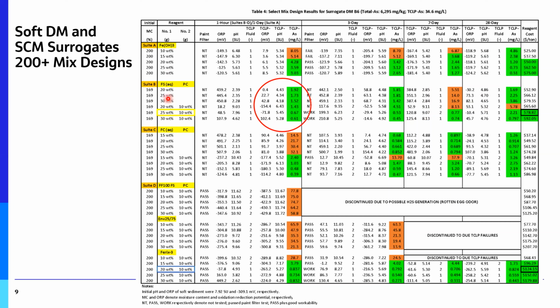For the ferric sulfate and cement combinations, we actually did pretty well here. At the upper doses, again aqueous, we found that 25 and 30% ferric sulfate with 10% Portland got us to a successful outcome. So let's take a look at another one.